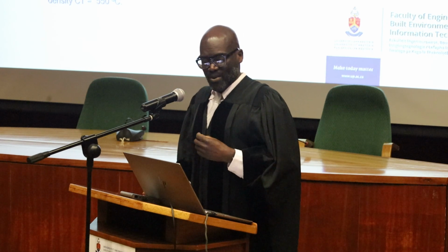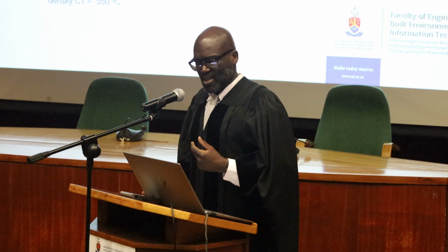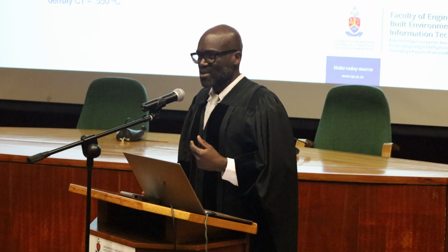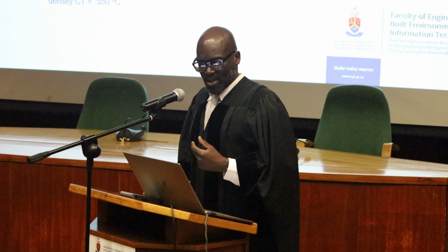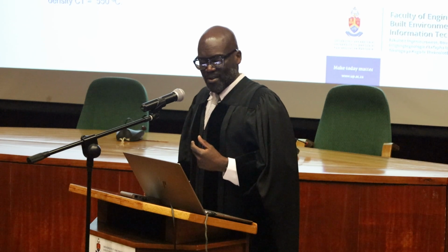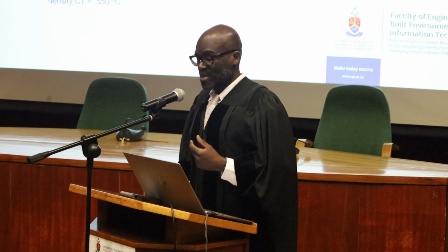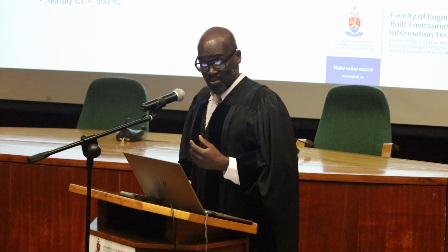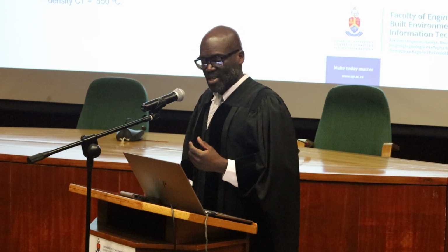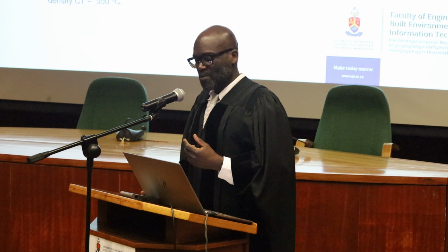Without necessarily going into details, you can actually see that this is a basket weave-like microstructure, what we call acicular ferrite. And this is polygonal ferrite plus acicular ferrite. So combining these microstructures plus very fine carbides, this is vanadium carbide, which is less than 100 nanometers in size, and combining it with titanium, niobium carbonitrides of that size,